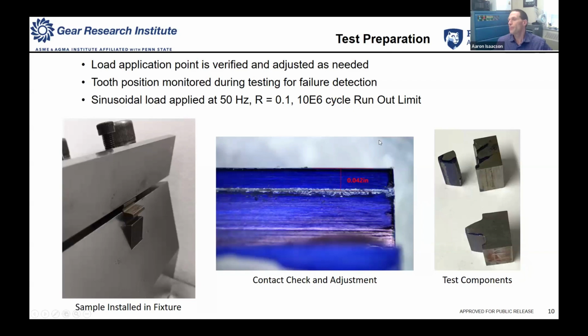So for the test, we're applying our sinusoidal load as we would in any sort of pulsator or single tooth bending fatigue test. Most of these are done at about 50 hertz. We use a stress reversal ratio, or an R value, of 0.1, which is the ratio of minimum to maximum load of 10%. And then our run out limit for this particular project, as with most of our projects, is 10 million cycles.